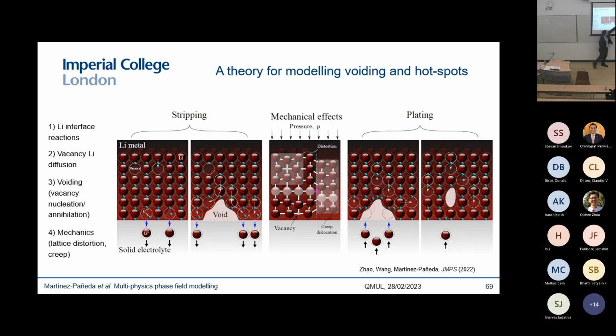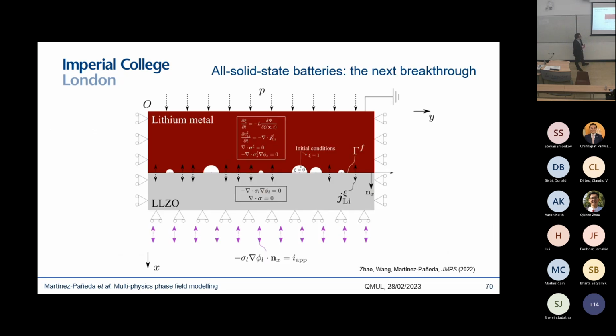So we need to capture those viscoplasticity effects and have a viscoplastic number. And this is the kind of problem that we solve. So again, a coupled electro-chemo-mechanical problem. We're solving the electro-chemo-mechanical problem both in the anode and the electrolyte, so we can naturally see those hotspots that I mentioned before. And you can see here the governing equations: a phase field equation for the voids, a transport equation, and then a mechanical problem and the electric problem.